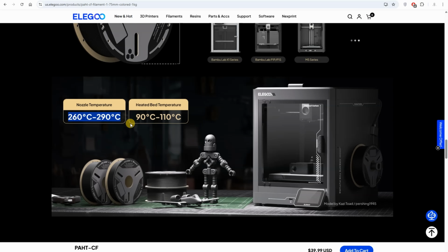Print settings: the nozzle temperature between 260 and 290 degrees Celsius, and the bed temperature between 90 and 110 degrees Celsius. And of course, we need a hardened steel nozzle.